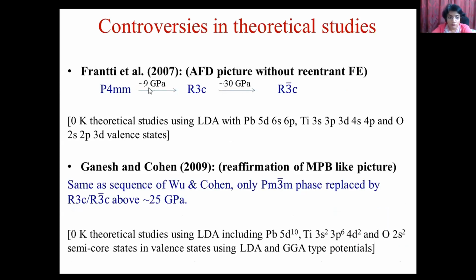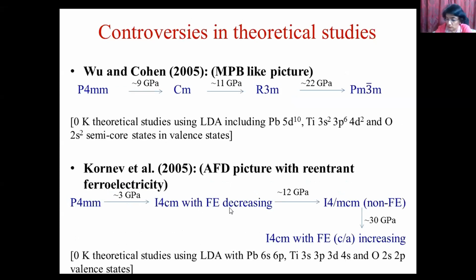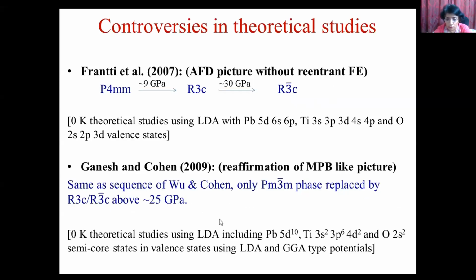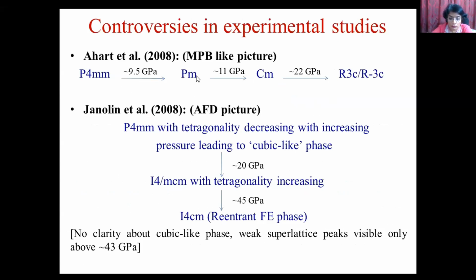Now, there are a few more studies. The third study is by Frantti et al., which says that the P4mm phase transforms to R3c and then R3c space groups, which involve AFD type transition, but there is no MPB-like transition to monoclinic phases. There is another study by Ganesh and Cohen. They have again confirmed the finding of Wu and Cohen, only this cubic-like phase has been replaced by the R3c space group. Talking about experimental pictures, the two pictures which I have already talked about have their own experimental support. The first group presents an experimental study in support of their theoretical picture, tetragonal to monoclinic to rhombohedral, whereas the